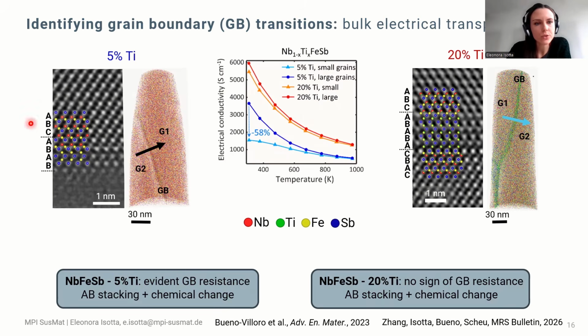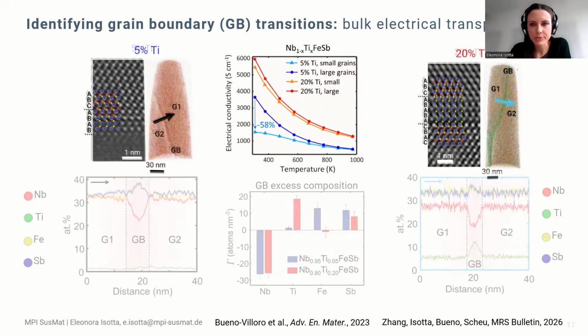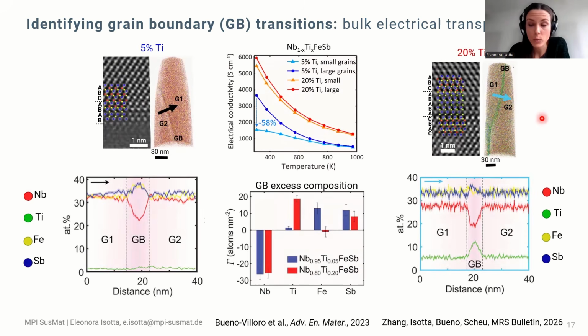It was first observed through high-resolution TEM that the grain boundary tended to have an AB stacking compared to the ABC stacking in the grain. This happened in both the 5% and the 20% titanium samples. What was different among the two types of samples was the chemical composition that formed at the boundary, because in the 5% titanium, the grain boundary happened to be rich in iron and antimony, whereas poor in niobium.